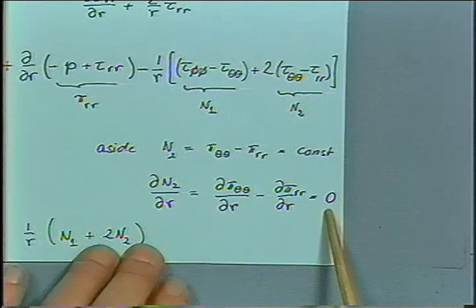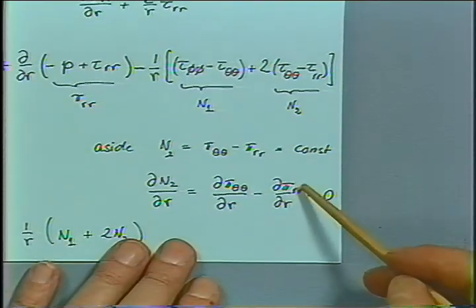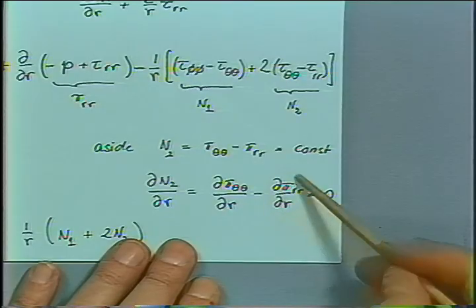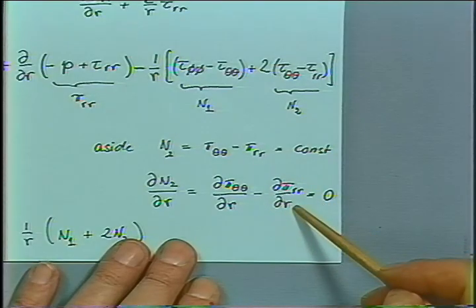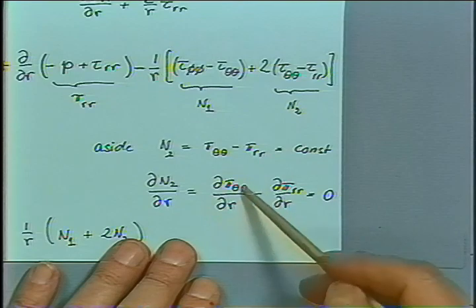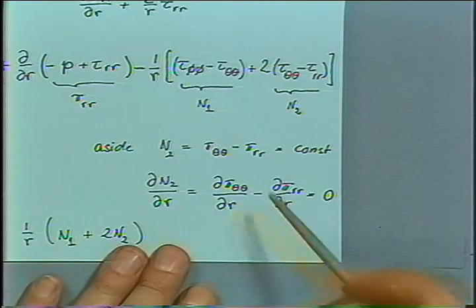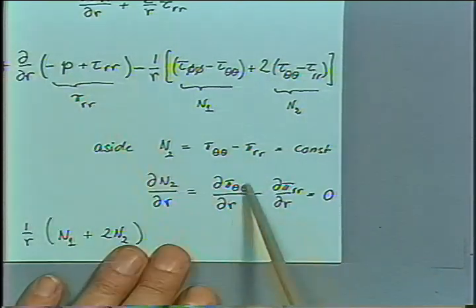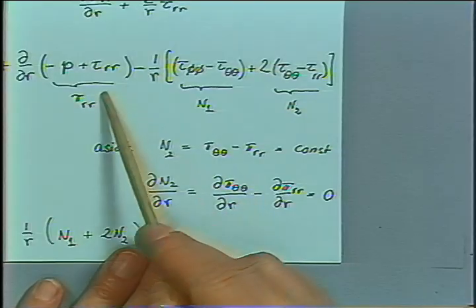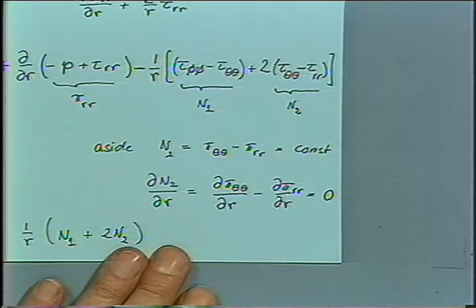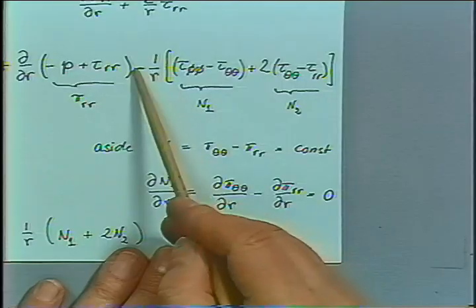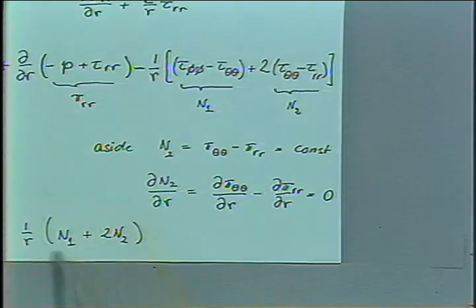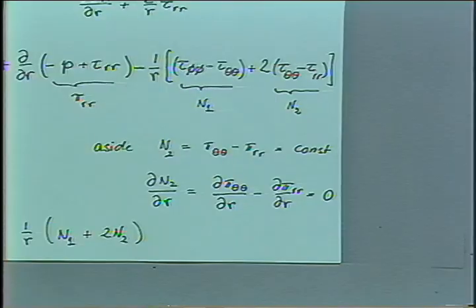So you can see that the derivative of tau rr in the radial direction is equal to the derivative of tau theta theta in the radial direction. And you can just replace this term with tau theta theta, and you put it on the other side to get rid of the minus sign, and you have the equation for the normal stress which we wanted to calculate. Okay? So this is the procedure.